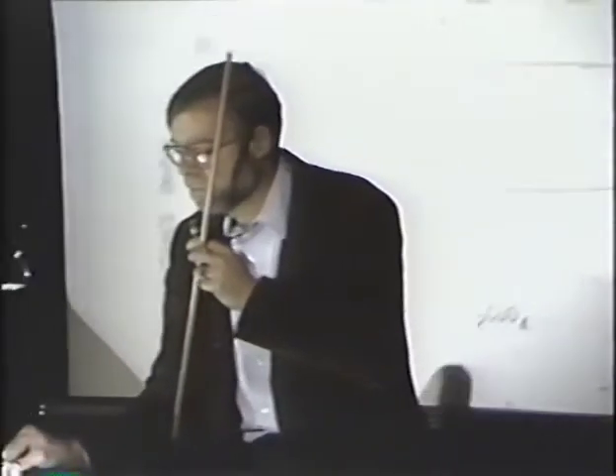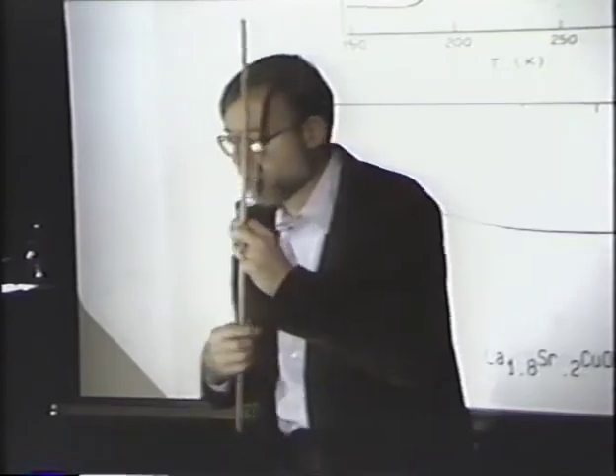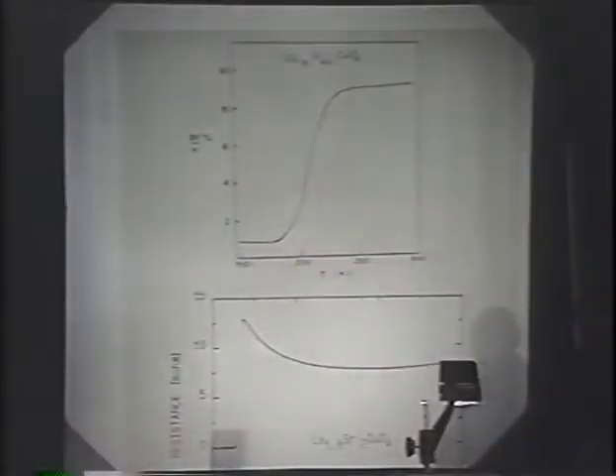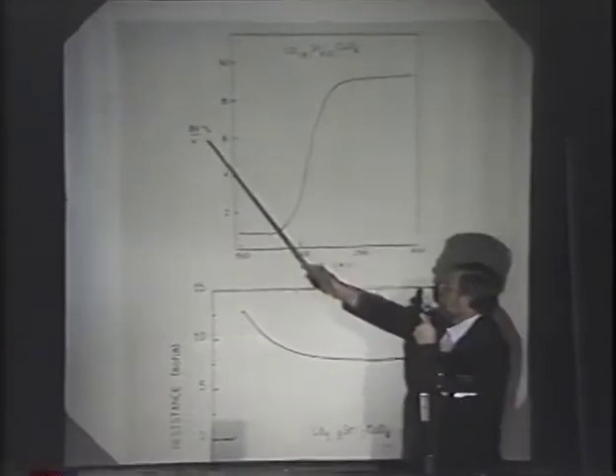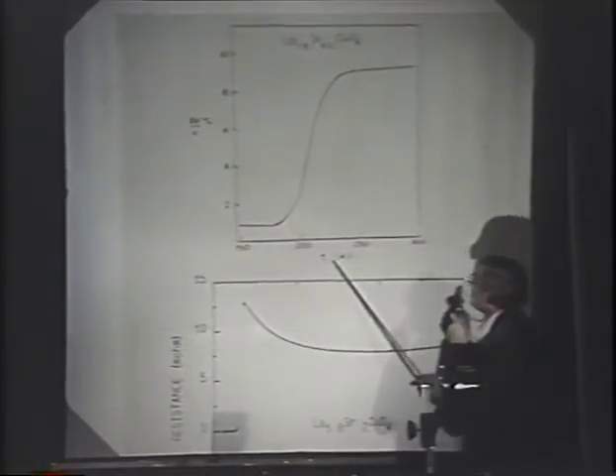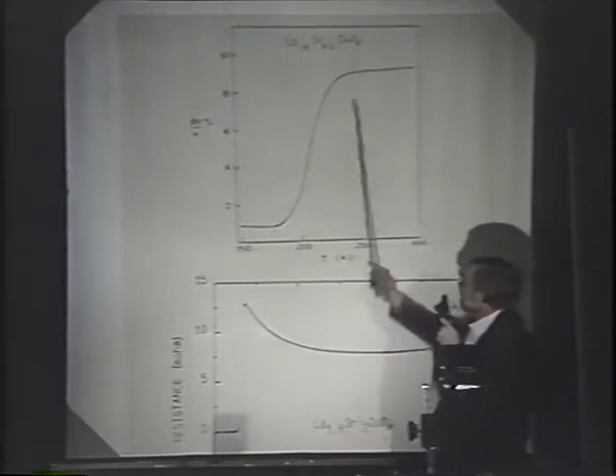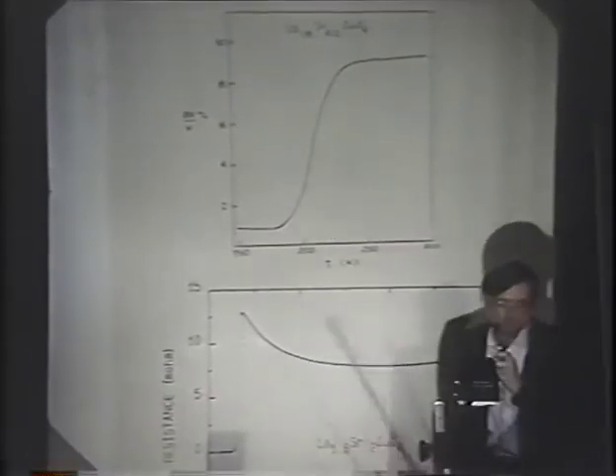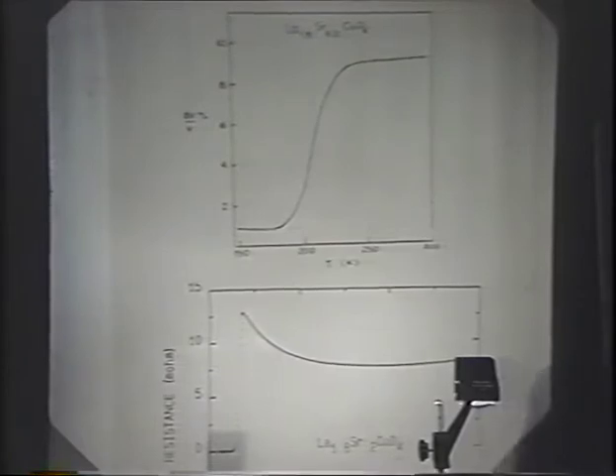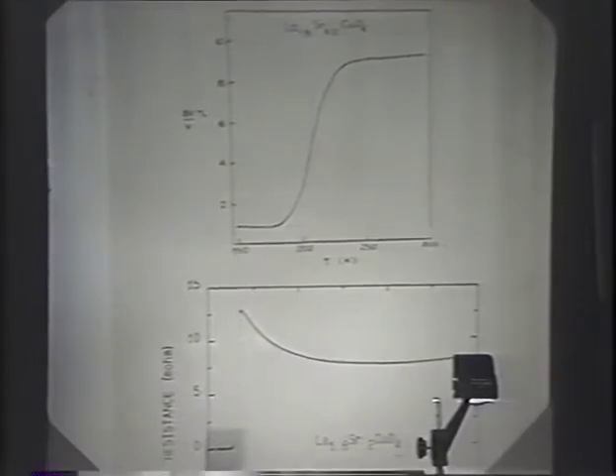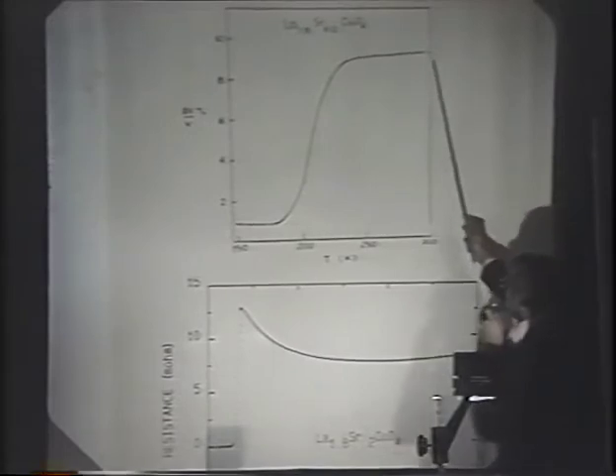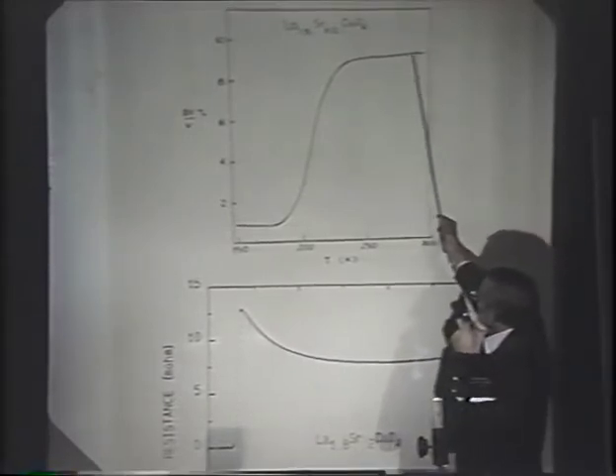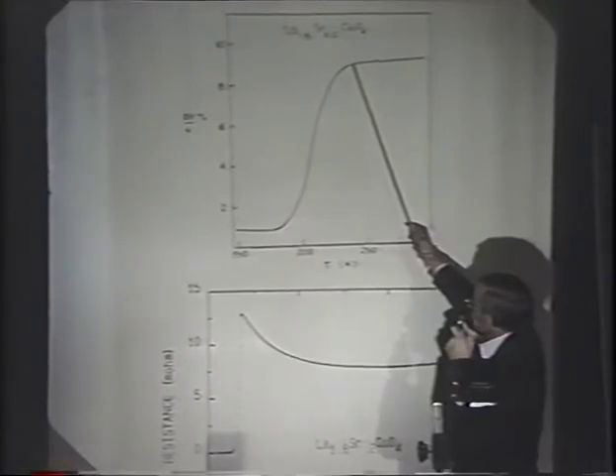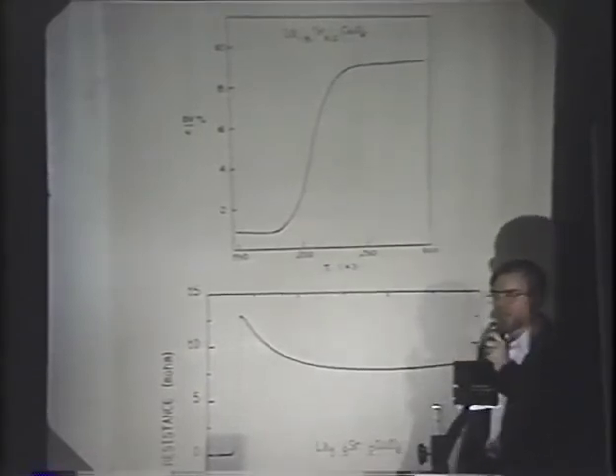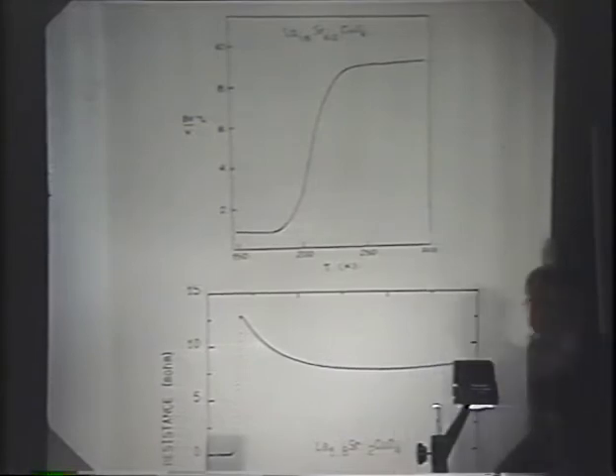I might point out some really interesting data that Shobo Bhattacharya took in the ultrasonic attenuation. This is a change in the sound velocity as a function of temperature, and this is an 8% change we're seeing over this temperature range. I guess the Argonne group has reported a lattice transformation occurring there. But if you look at this curve, it's really interesting. The sample actually appears to get softer as you cool, and then it transforms to a phase that is even softer than that. So that's kind of unusual.